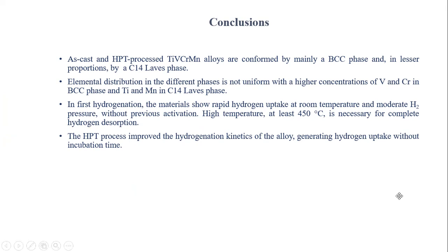A high temperature, at least 450 degrees Celsius, is necessary to complete hydrogen desorption. The HPT process improves the hydrogenation kinetics of the alloy, generating hydrogen uptake without an incubation time.